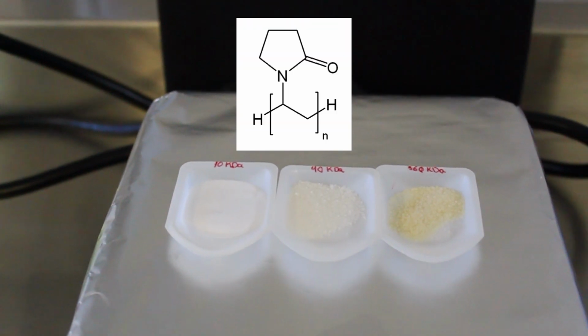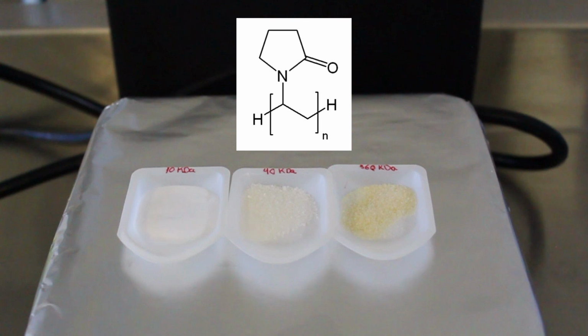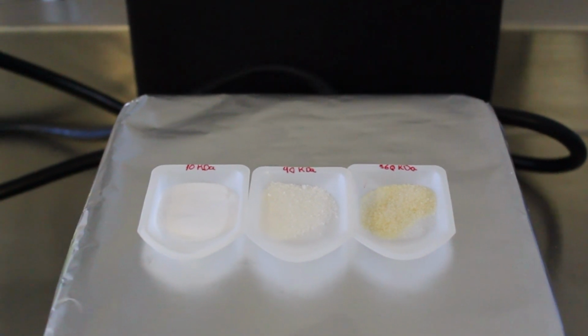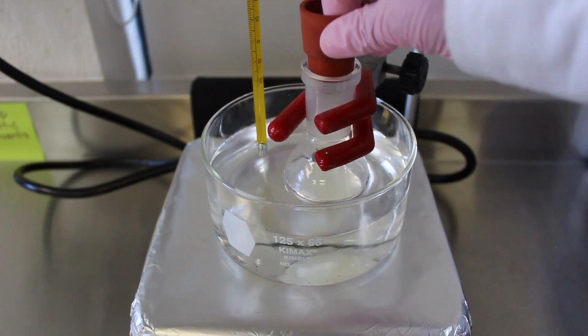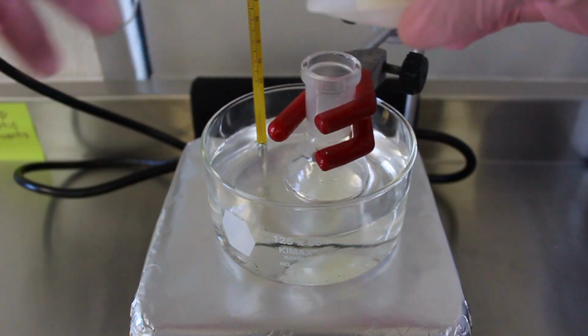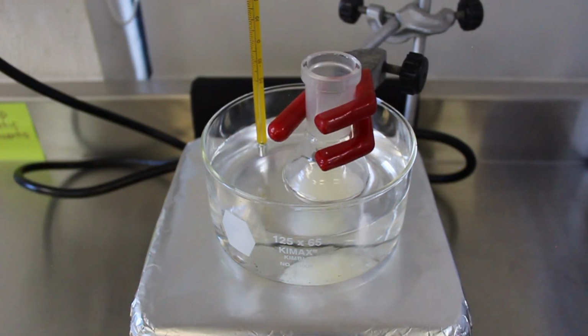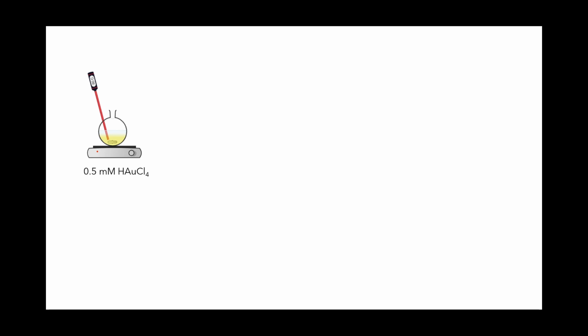Specifically, we evaluated the effect of three different molecular weights of polyvinylpyrrolidone in the morphology, size, and stability of gold nanoparticles synthesized in a nonaqueous media. We started with a 0.5 millimolar gold precursor solution in this, with heating and stirring. Once the solution was homogeneous, 1 weight% of polyvinylpyrrolidone was added with vigorous stirring.